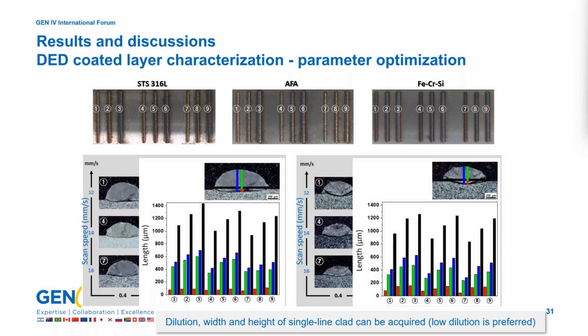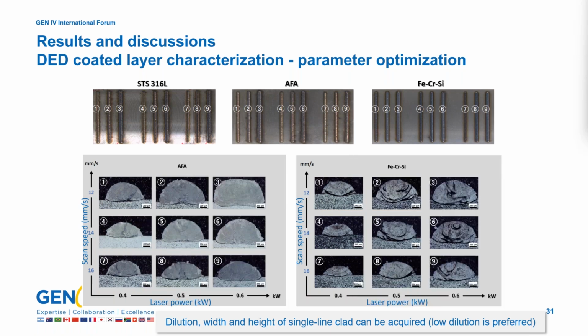In this study, low dilution is preferred. When fabricating dual-layer coated materials, processing conditions with low laser power are advantageous, considering the bead size and dilution rate, because the layer thickness will probably be limited. Therefore, it is determined that the process conditions of specimen 4 and 7, where the single line clad width, height, and penetration depth are relatively small, are selected as the optimal conditions.